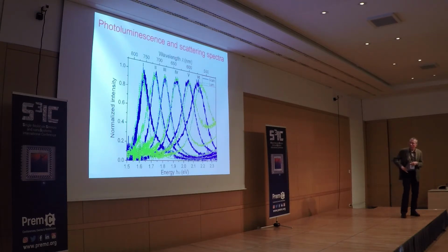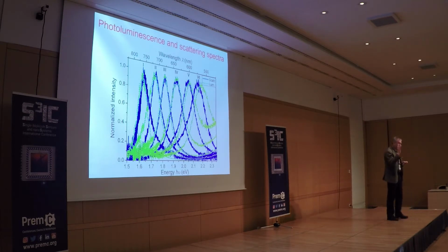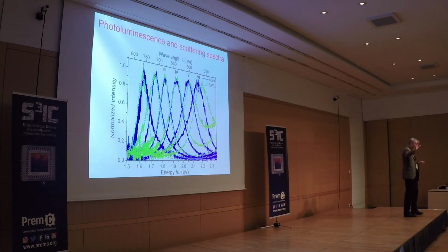So what you see here is a number of gold nanorods with their scattering spectra, white light scattering in blue, and on top of each of these blue spectra, the green spectra corresponding to photoluminescence. And as you see immediately, this photoluminescence in my world is just excitation of the gold nanorod with a given wavelength, in this case 532 or 514 or 488, typical laser lines. And you look at which wavelengths are emitted by the gold particle.